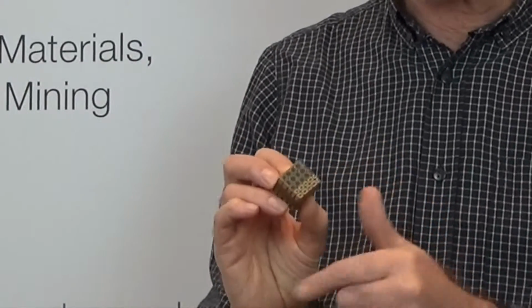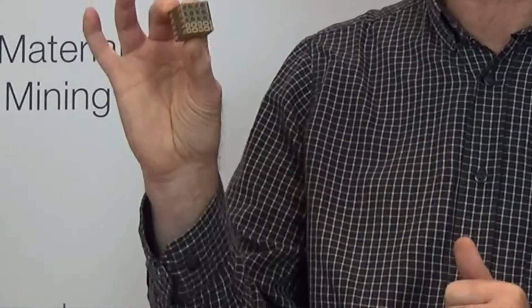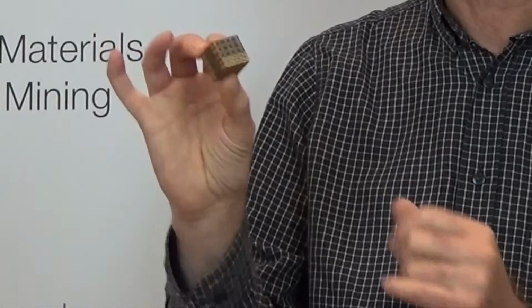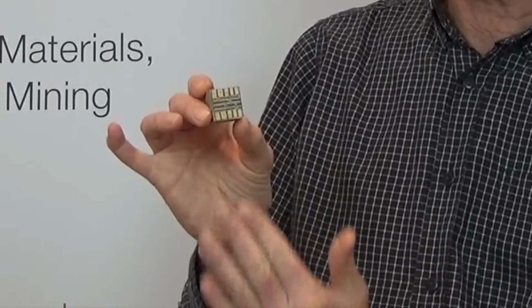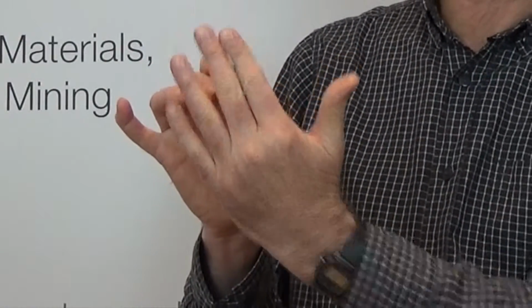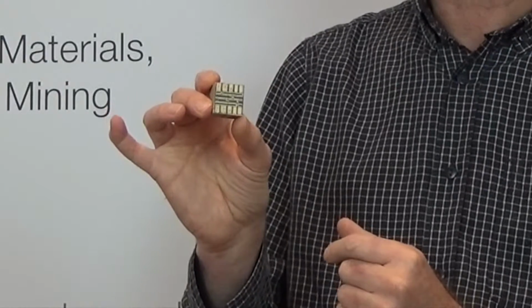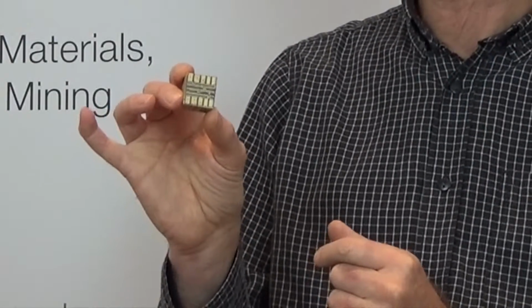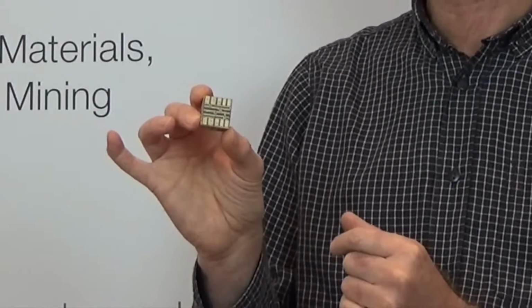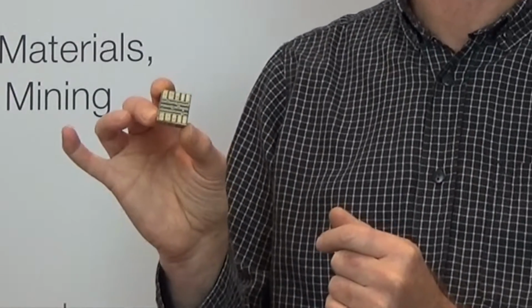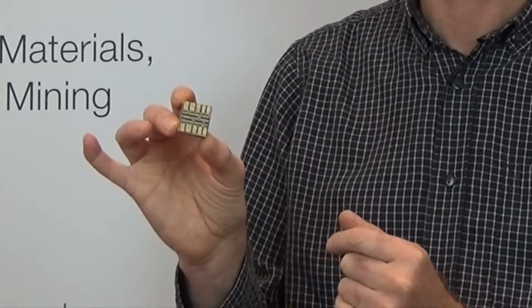If we look at the structure of wood, we can see in cross-section that it's made out of hollow cells represented on this little wooden cube. There are longitudinal cells, the maximum stiffness is in that direction, and indeed the cellulose, which is the stiff component of the wood cell wall, has an elastic modulus of about 138 gigapascals.